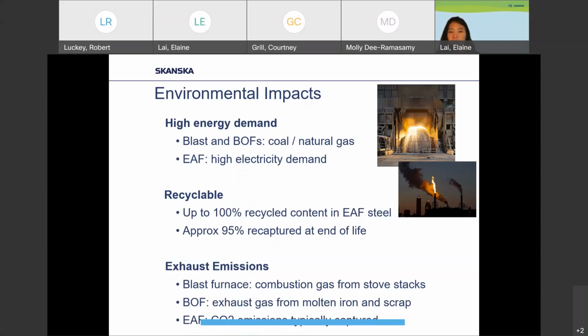Delving a little bit further into the environmental impacts, BOFs rely predominantly on combustion of fossil fuels, often to heat the furnace above 2,600 degrees Fahrenheit. Again, as I mentioned, the EAFs, electric arc furnaces, by their nature, are powered by electricity. So again, the carbon intensity is largely determined by the grid mix in that region. Fossil fuels in EAF steelmaking account on average, in the US, for about 33% of the grid mix. The Pacific Northwest we're seeing is some of the cleanest because of the large role that hydropower has.